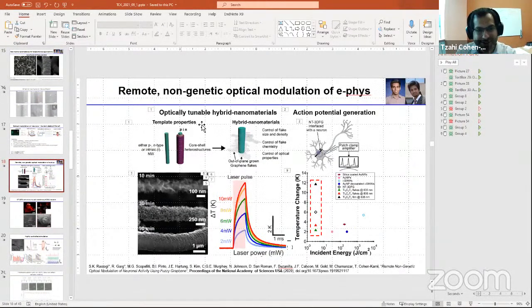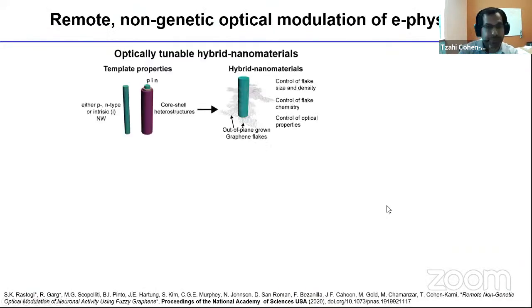This part of the talk is work in progress. Actually, Boje already showed it in his own work. We are trying to see whether coating this with graphene will make them more efficient. Essentially, if you shine light on this standalone structure, you'll have charge separation. You'll have electrons in the shell, and you'll have holes in the core. And this will depolarize the membrane by mirror charges on the membrane side. You'll have the same idea of transient current forming.